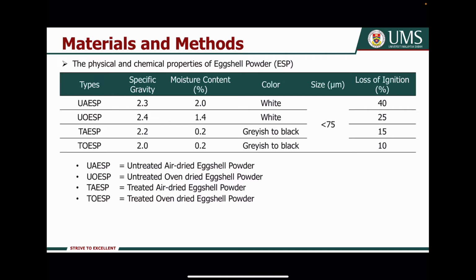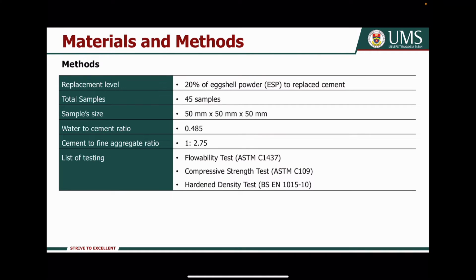This is the physical and chemical properties of the eggshell powder. As you can see, the specific gravity, moisture content, and loss on ignition for the treated eggshell is significantly lower compared to the untreated eggshell powder. I only used 20% of eggshell powder to replace the cement and a total of 45 samples. The sample size is a 50 by 50 by 50 mm cube. The water to cement ratio is 0.485, and the cement to fine aggregate ratio is 1 to 2.75.